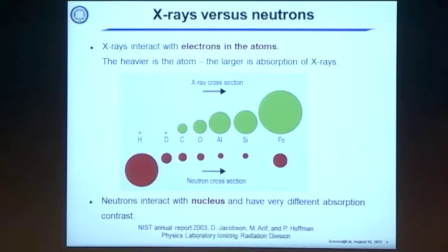So what I'm showing here is a cross-section. The diameter of each of those spheres is proportional to the probability of a neutron or X-ray to be absorbed. The green ones are for X-rays and red for the neutrons. As you can see, for hydrogen, for example, which is the lightest element, X-rays have almost no interaction because there is only one electron. But neutrons have the highest probability to be absorbed by hydrogen. At the same time, look at iron, which is on the right-hand side. X-rays can interact with iron very strongly, and get absorbed very easily or scattered. But the neutrons can penetrate quite a thick amount of iron, and still can see hydrogen within an iron